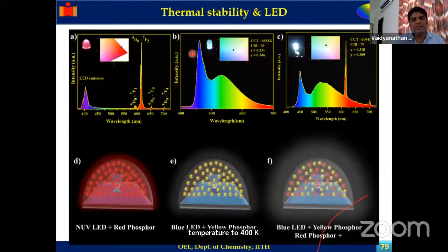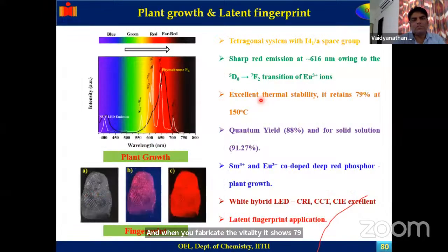When you fabricate the white LED, it shows a CRI of 79%. And the red LED is also promising. It shows a sharp red emission. We can also use it for fingerprint application. Our compound is white in color. Under a UV lamp, at 254 nanometer it shows this color, and at 365 we get a very nice color. So that means it can be used for latent fingerprint application also.